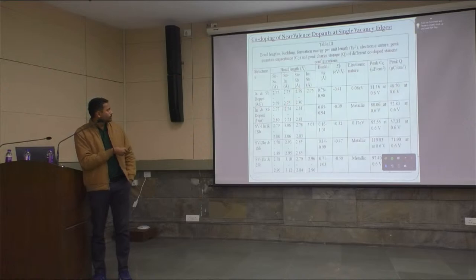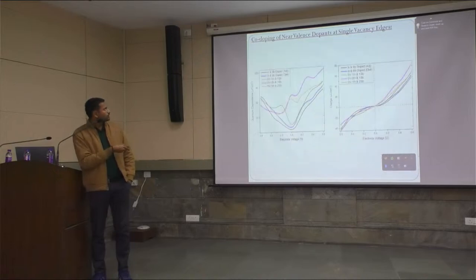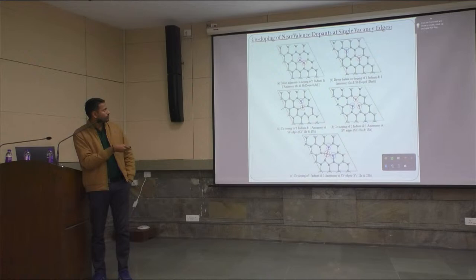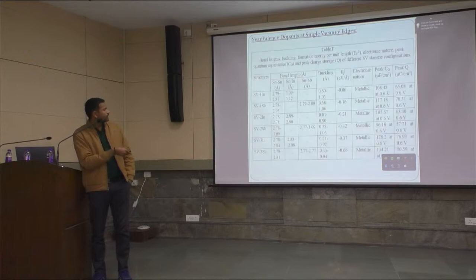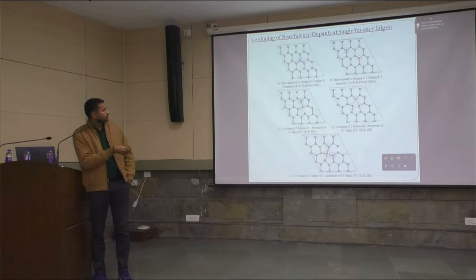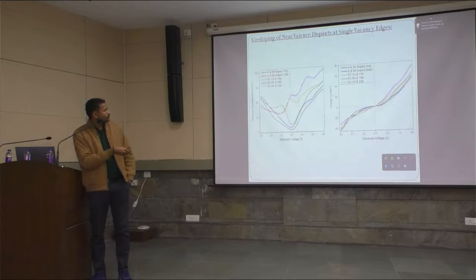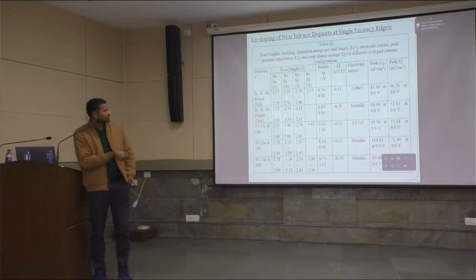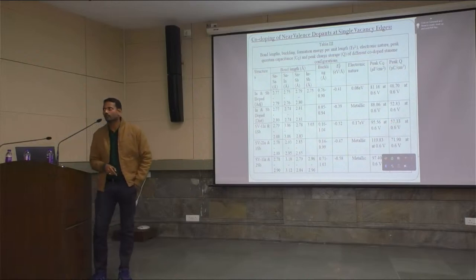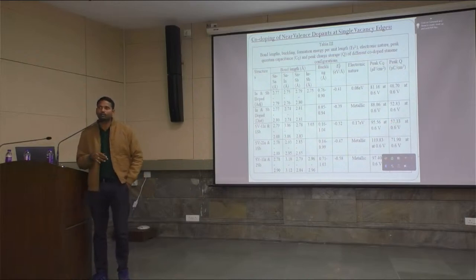Looking at the stability data and the quantum capacitance data, the quantum capacitance peaks are lower in comparison to the individual dopants. When we dope the individual dopants at the SV edges, we are having better quantum capacitance. But when we are co-doping indium and antimony, the quantum capacitance peaks are less. So we can say that instead of co-doping, it's better to go with antimony doping in stanene.